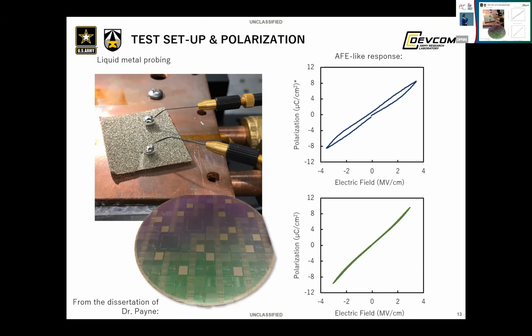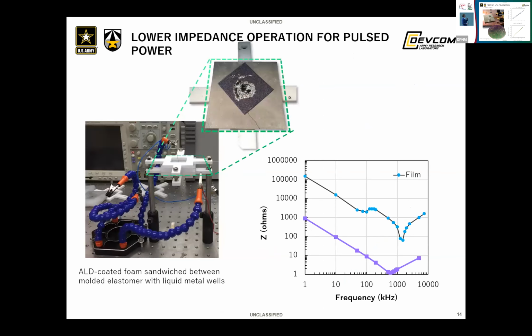Now, this composition, we compared it, this was a wafer that was fabricated with the same composition. And we have to have arguments about it, but there is some nonlinearity here. And so we felt like, okay, the material that we were getting when it wasn't shorted was at least something that was indicative of what we could get in our high quality 6-inch fab process.